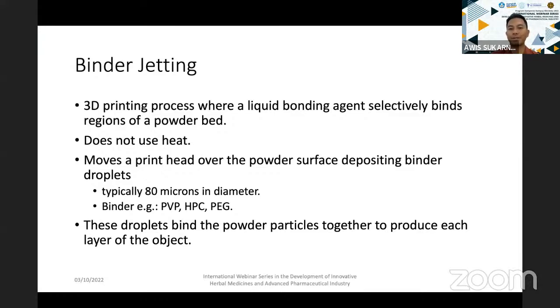So the first thing you do is spread a thin layer of powder. After that, you drop a liquid bonding agent, which means a binder. The binder acts like a glue. You drop the binder on top of the powder, and then you apply another thin layer of powder on top of the first layer. Because you already put the glue, the glue bonds the first and second layers together. Then you just repeat the process: drop the binder on top of the powder, then stack another powder layer on top of that, until it becomes a 3D object.